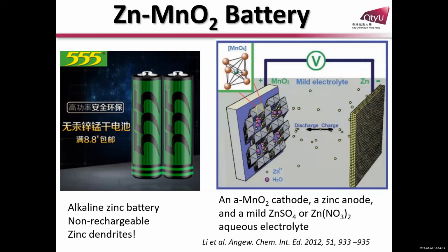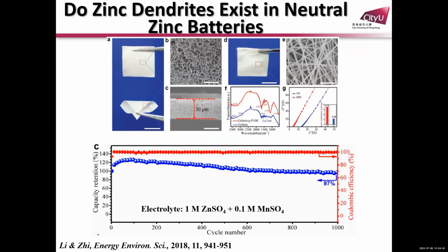Nowadays, dry batteries still use zinc. We call it zinc manganese oxide or zinc carbon. The technology is based on zinc, and then people started to make it rechargeable. For example, this one uses alpha manganese oxide together with zinc sulfate as electrolyte to make it rechargeable. After that, this is my research: we use carbon nanotubes mixed with manganese oxide and a hydrogel electrolyte, which improved the cycling stability to 1,000 cycles. Even with no treatment, the zinc anode is still quite stable in this system.